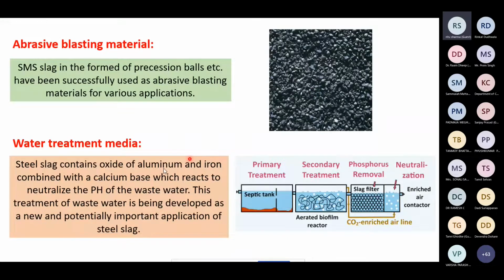This slag contains oxide of aluminum sometimes and iron oxides also, so that can be utilized as water treatment media. If it doesn't contain chromium and manganese, and only contains aluminum and iron, then it can be utilized as water treatment media by adjusting the pH and other means. So slag filter is there, that is utilized in many research studies. I found that they have utilized it successfully, but provided that other impurities are not present.